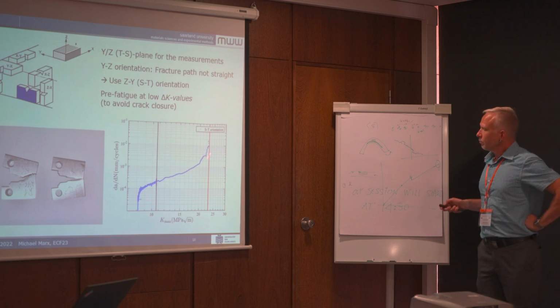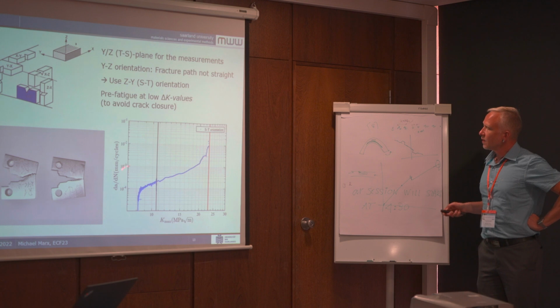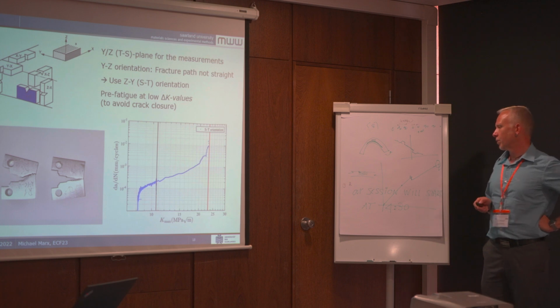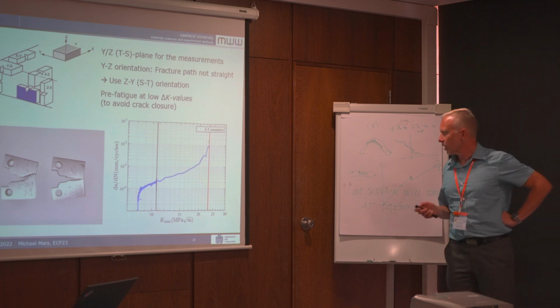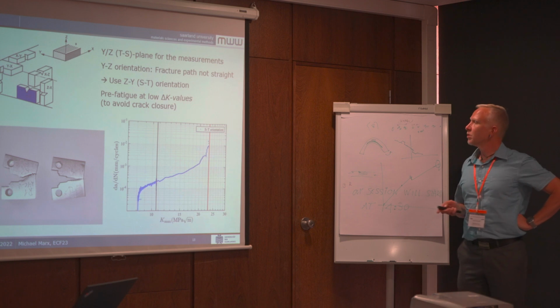And here, this is our da/dN diagram. This was from the fatigue testing of a similar specimen, and as I mentioned before, we pre-fatigued our specimen and then we loaded it here at a little bit more than 10 megapascals per square root meter.